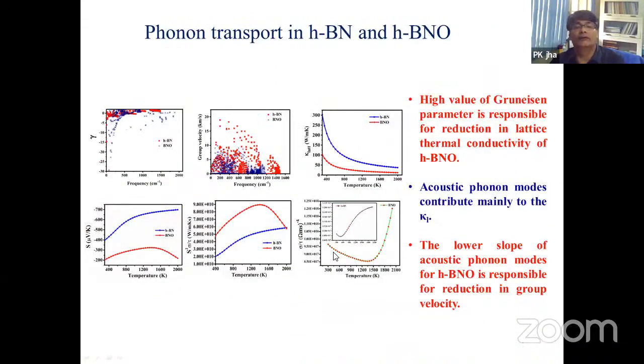So you can see that these are the parameters which basically lead to the reduction in the lattice thermal conductivity. These are all parameters we have explained anyway. Just look here at hexagonal boron nitride and boron nitride oxide: the K lattice for the boron nitride oxide is much lower, right? At room temperature it is 100, while for the hexagonal boron nitride it is around 300, right? So a high value of Grüneisen parameter is responsible for the reduction in lattice thermal conductivity in hexagonal boron nitride oxide. Acoustic phonon modes contribute mainly to the lattice thermal conductivity. The lower slope of the acoustic phonon mode for hexagonal boron nitride oxide is responsible for the reduction in group velocity. That will lead to the lower lattice thermal conductivity, and finally.